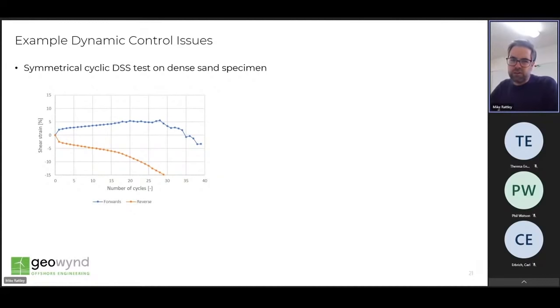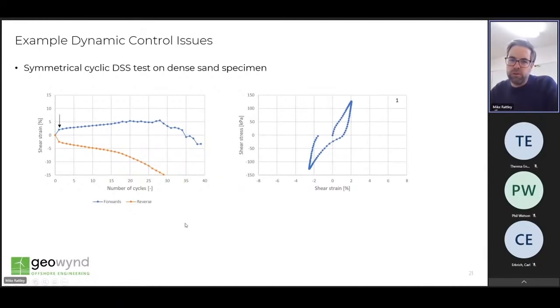Now, problems can occur as a result, and this slide illustrates a common dynamic control issue for a stress-controlled two-way cyclic loading test on a medium to dense sand, which is a tricky beast to test in the DSS apparatus. This is a test in which the forward and reverse shear stress amplitudes are equal. The plot on the left here illustrates the changes in peak forward and reverse strain with number of loading cycles. And the plot on the right here shows the stress strain response measured during each individual load cycle.